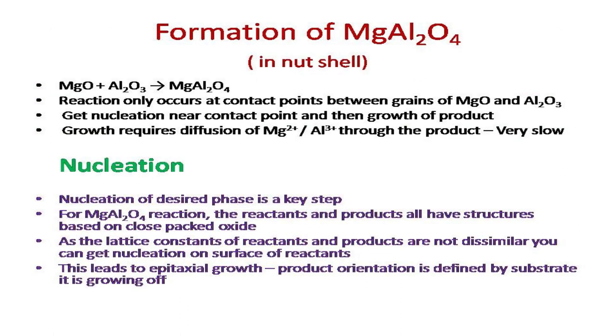Moving on to the formation of MgAl2O4, in a nutshell, if we put whatever we have seen so far in the form of a summary, MgO plus alumina react together to form a spinel called MgAl2O4. The reaction only occurs at contact points between grains of MgO and Al2O3. Nucleation occurs near the contact point and then grows into the product. This growth requires diffusion of magnesium and aluminum ions through the product layer, which is itself a very slow process, and that's why this reaction takes a very long time. That was the formation of MgAl2O4.